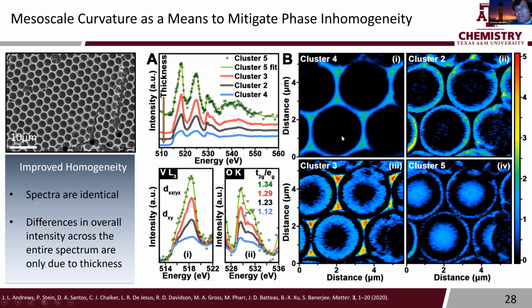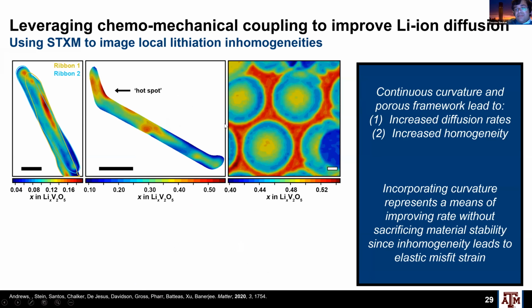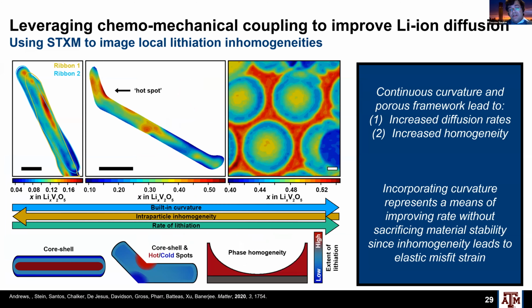Okay, so no matter where you look across these millimeter-sized domains, you see very homogeneous signatures in the vanadium L3 and oxygen K-edge spectra. And with that, the only differences, of course, are due to overall density, but the line shapes are the same. So essentially what we've been able to do is, by using curvature, we can improve the rate performance, because we've got a very large area of electrolyte contact and the diffusion path lengths are decreased. And we are also getting homogeneous lithiation take place across the entire structure, but without generating this elastic misfit strain that we observe across all of these single particles, these single wires, right?